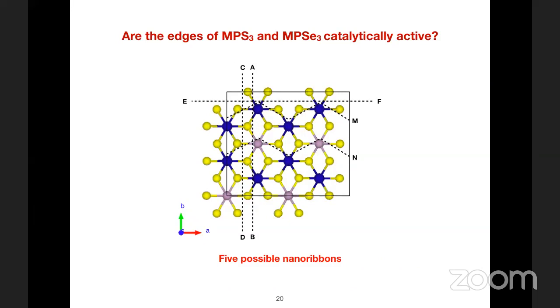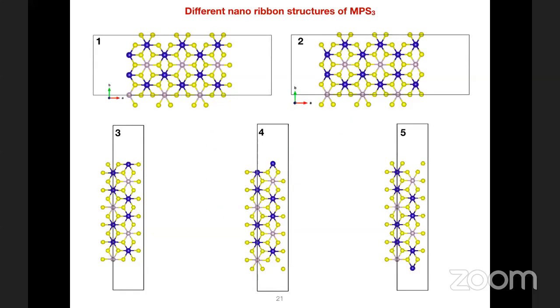For that, we study the catalytic activity at the edges of these compounds. Now, I cannot describe all the details, but if you look at the structure carefully, you will find that you can cut it along these 5 lines indicated on this figure to create different nanoribbons, always maintaining the stoichiometry in your structure. So there are 5 possible nanoribbons that one can create. They would look like this.